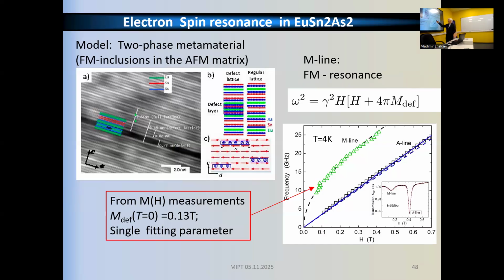We try to fit the experimental data of this M line, but for this we need certain parameters, which are not easy to take from measurements. We know the magnetization is the magnetization of the defect field. It's not easy to obtain. From the magnetization and hysteresis measurements I showed, we can only estimate it, to be an order of magnitude smaller than the antiferromagnetic magnetization. But here we use it as a fitting parameter and obtain 0.13, which is a reasonable number. Now with this single fitting parameter, we obtain quite a reasonable fit of the experimental data.